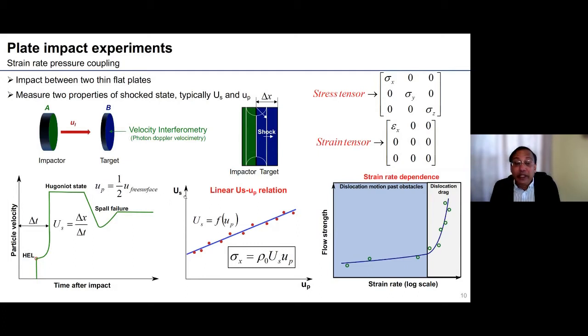As I mentioned, one of the primary uses for such work is to create the so-called equation of state, which is the relation between the particle velocity and the shock wave speed. The shock wave speed can be measured by the arrival time at the free surface, and the particle velocity is measured from the free surface velocity. And then normally one sees a linear Us-Up relation, that's the linear relation between the shock wave speed and the particle velocity. One can obtain the normal stress by using the jump conditions, or the Rankine-Hugoniot conditions, using the formula of the density times the shock wave speed times the particle velocity.